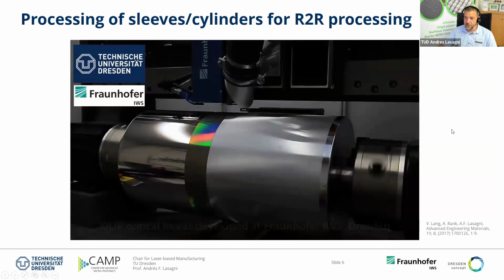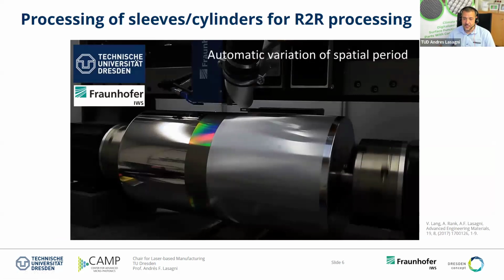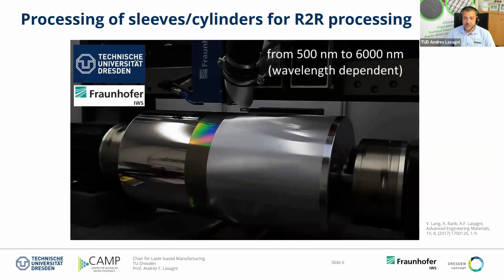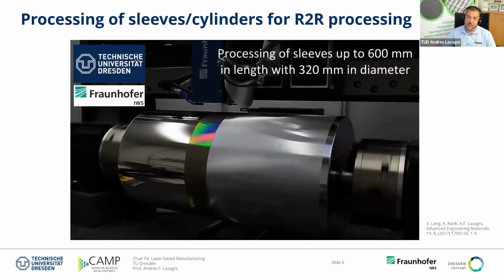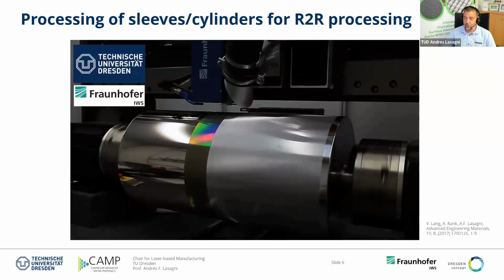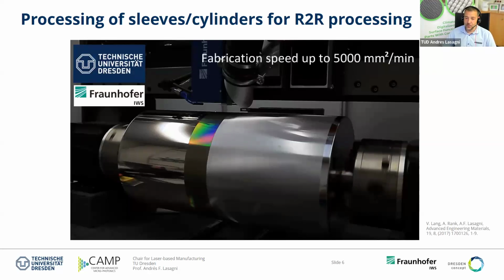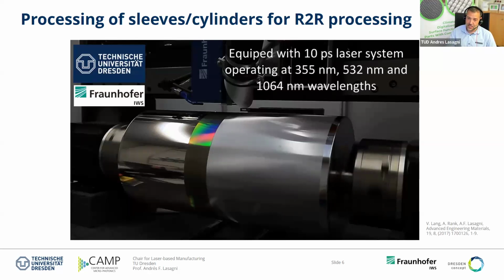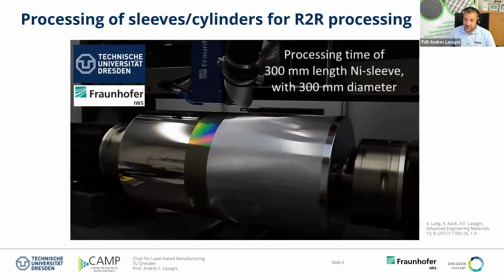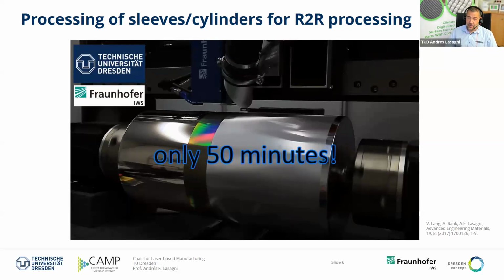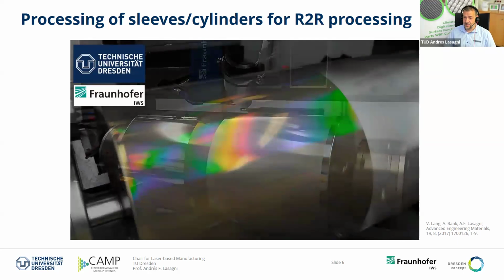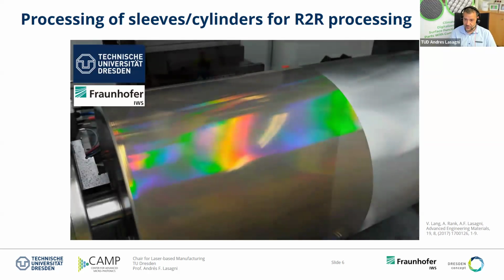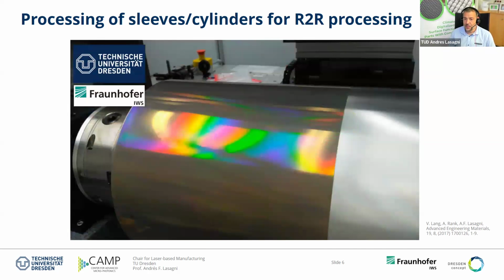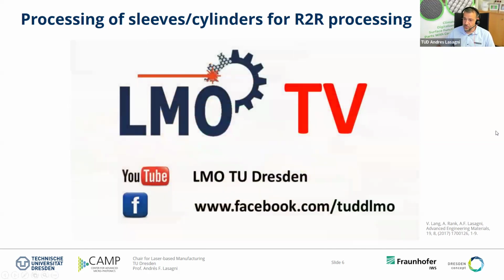So just that you see some of what we are doing at the University of Dresden. I hope you can see the video running, but this is a system where, for example, we are texturing cylinders, and these cylinders are then implemented in roll-to-roll applications, where we are capable of transferring the texture from the sleeve, from the cylinder, to, for example, a polymer foil. And you see here, the structuring process can be long. It can take some time. In this case, for a 30 centimeters in diameter and 30 centimeters long sleeve, we need about 50 minutes, almost 1 hour. You see the change of the color due to the periodic structures.